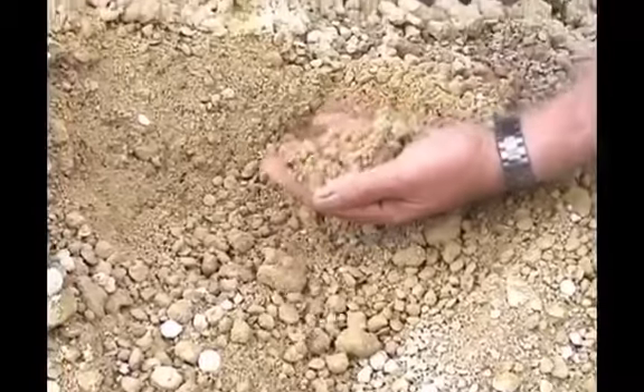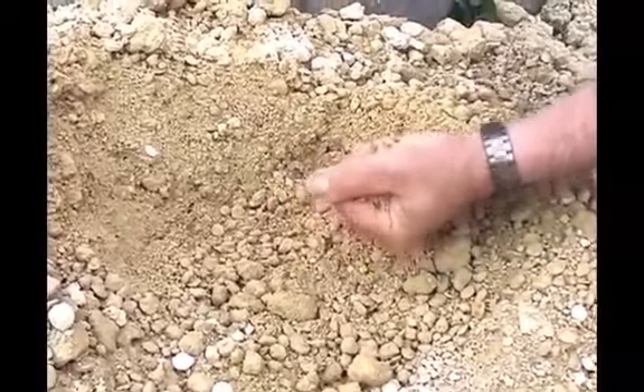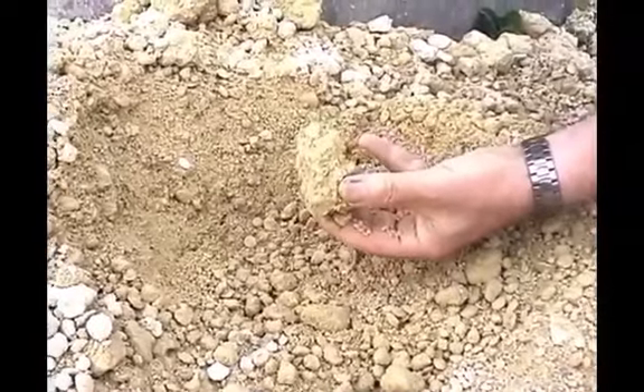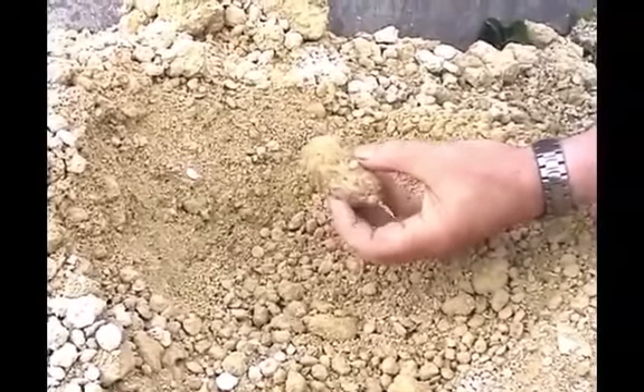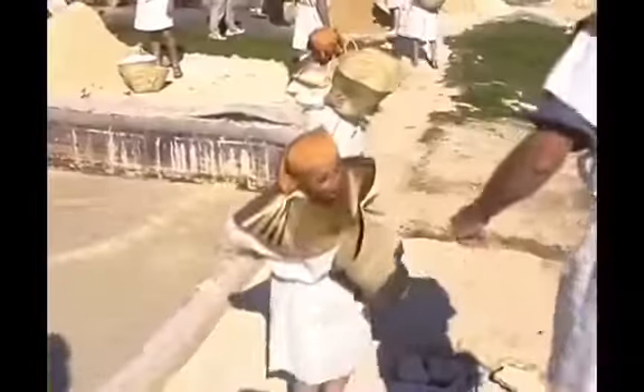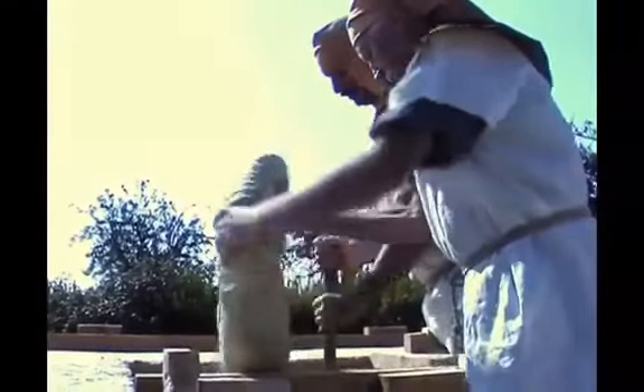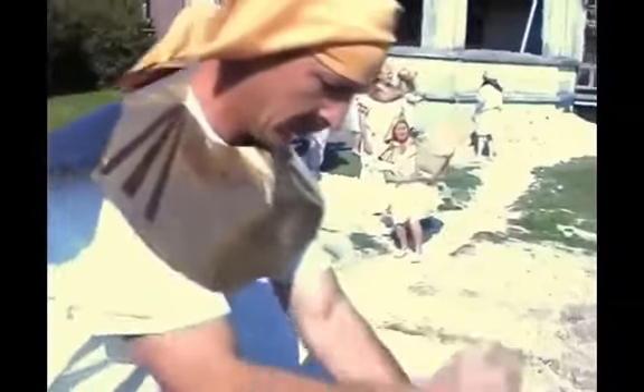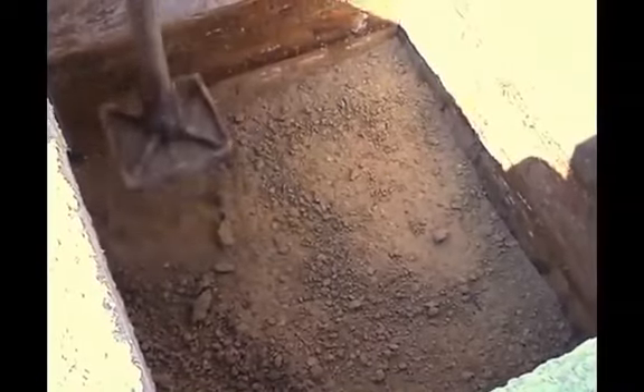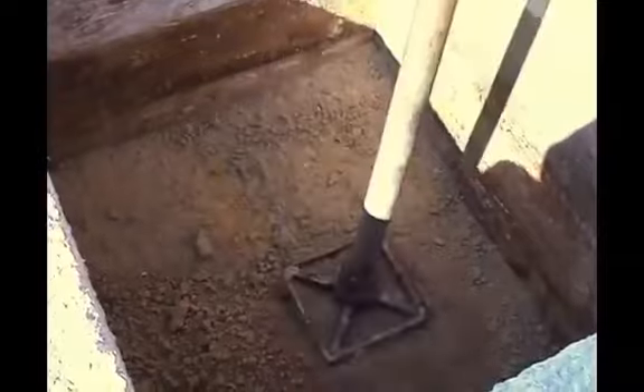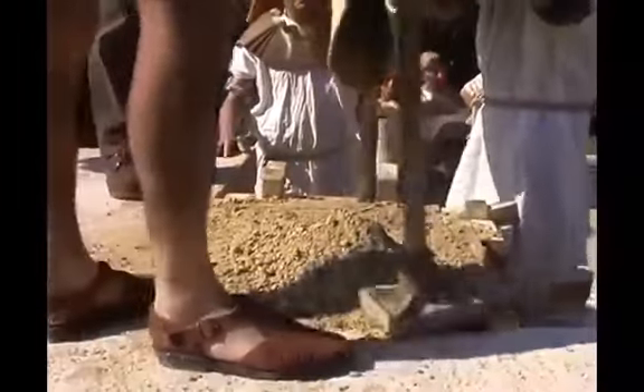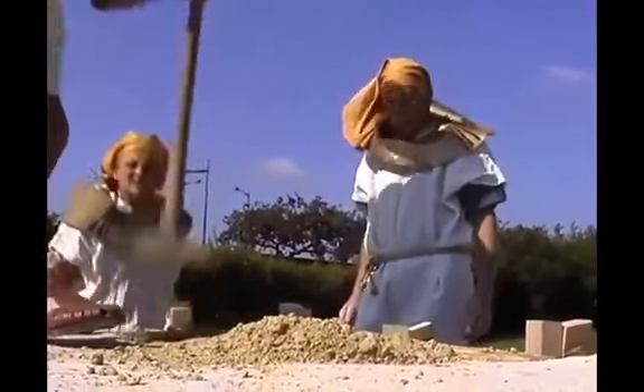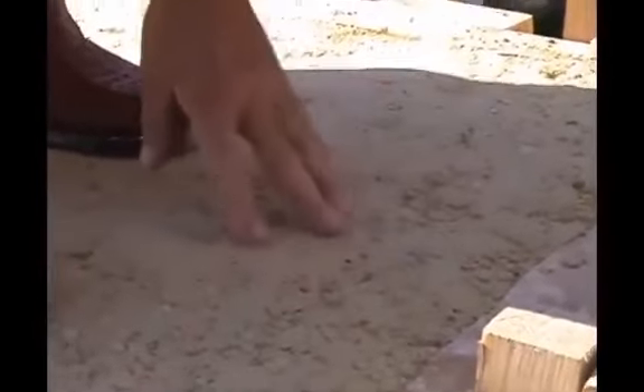Inspecting the mixture, 95% limestone aggregates and only 5% rock-making binder. Between 12 and 17% of water give it the consistency of wet sand. One squeezes the mixture with his hand and it keeps its shape. This batch will quickly gain strength. We do all of the work manually, forming a human chain carrying buckets from the mixing area to the mold. We pour the limestone concrete mixture in a mold and pack it down with a tool called a rammer. Compacting the material requires little effort. The packing operation encourages cohesion and the denser mixture takes on high strength from the initial curing phase.